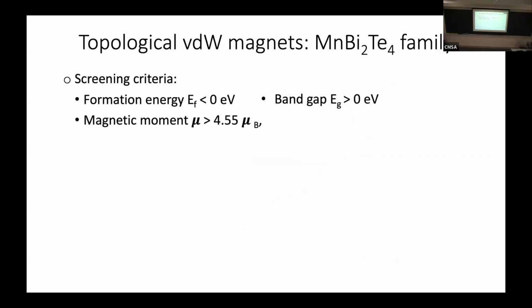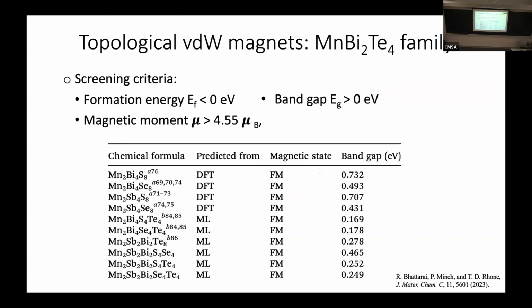We can then do some screening, selecting criteria for finding a good set of materials, and then make a model to predict both formation energy and magnetic moment, quickly generate a large set of interesting materials and their corresponding properties, and then find the best candidates, and then check the results with additional DFT. We found good agreement between our machine learning predictions and our DFT, or first principles, validations.